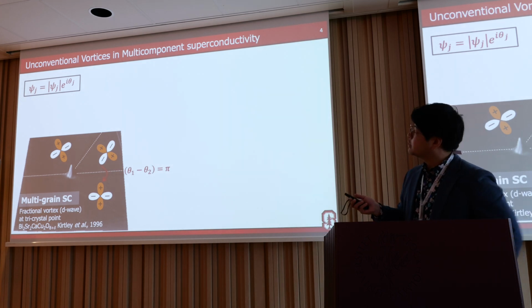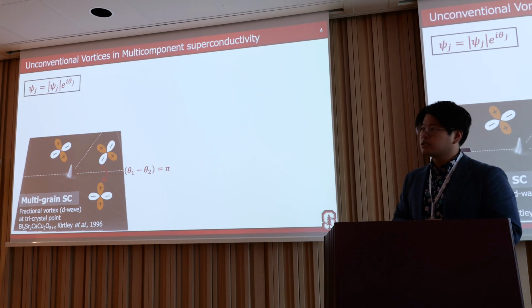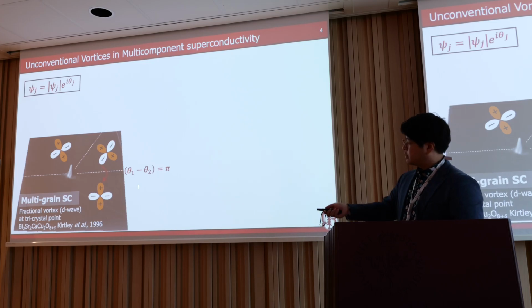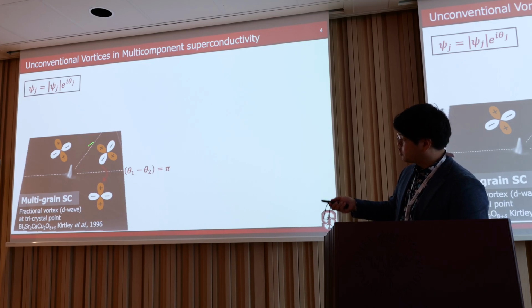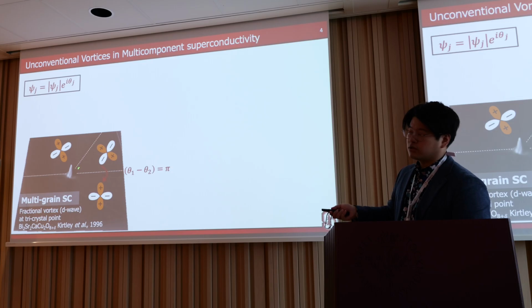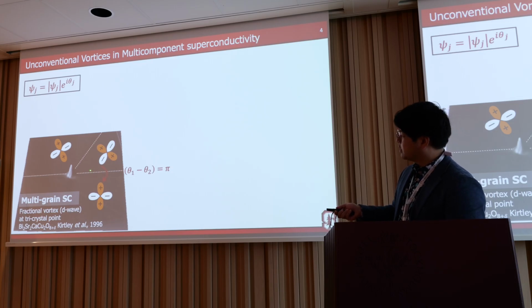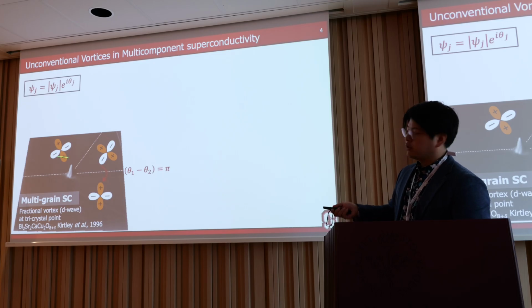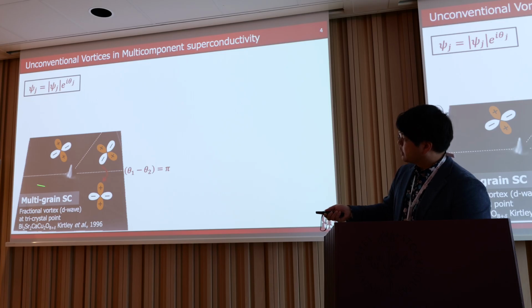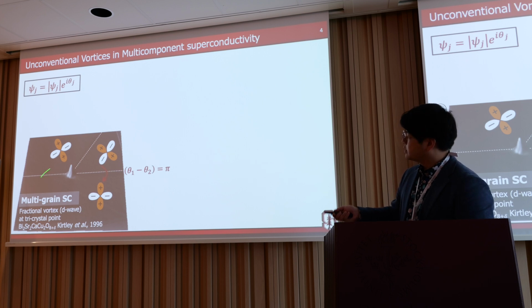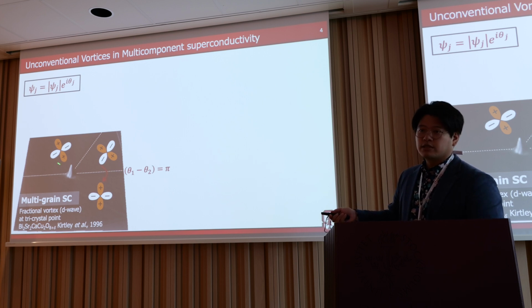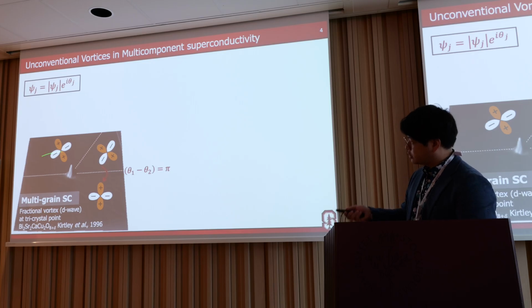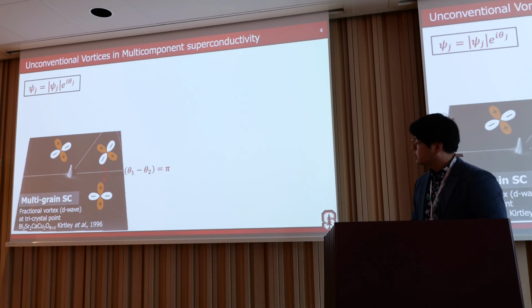I will show some examples of the unconventional vortex state in multicomponent systems. This is the well-known cuprate measurement, the tricrystal junctions. It's the same film, and the cuprate has a different crystal orientation, so a very specially designed system. This is a zero field scanning SQUID microscope measurement. It naturally gets the pi phase winding around this point, so we see that the half integer fractional vortex is stable at this point. So it's strong evidence for d-wave superconductivity.